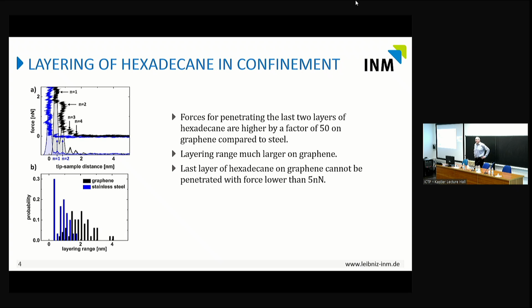And what we have done then is we have taken so-called force distance curves. So we approach in hexadecane the AFM tip to the surface. We plot here the tip sample distance, so we have subtracted the bending of the cantilever. And what you see on the upper graph is the force versus tip sample distance. The blue curve is above steel. So what you can see is there's no force, no force, no force, no force. Then there's a little hiccup just before the steel, and then there's the hard wall of the steel.